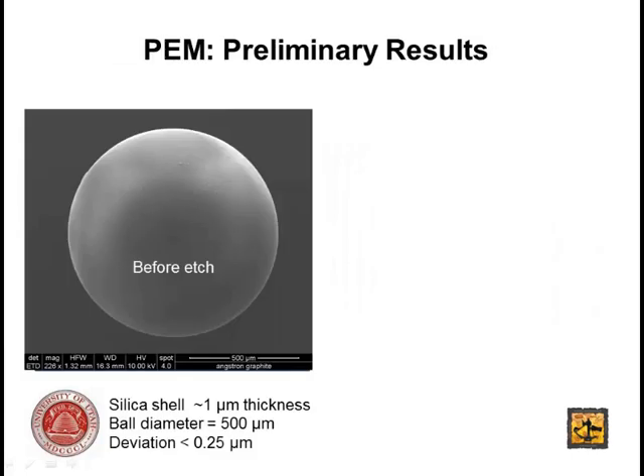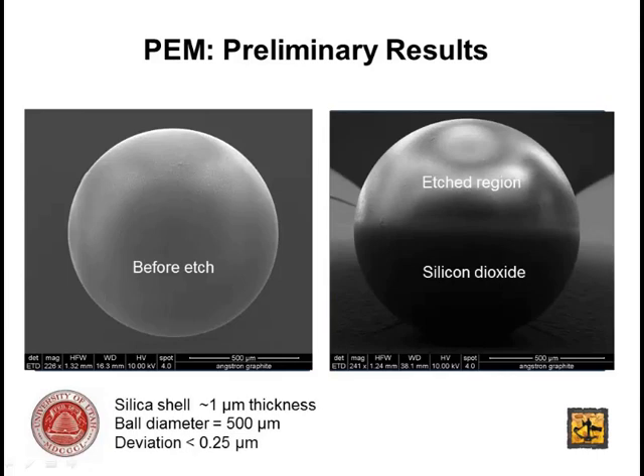Okay, so what do you get out of this? After sputtering the films, you get a lens with a coating, and it looks pretty uniform before the etch. Then after you immobilize and etch this, you get something that looks like this. This has been etched using ion milling, so you remove the top 2 layers, and the silicon dioxide looks kind of darker here than here, and I have better pictures of this.